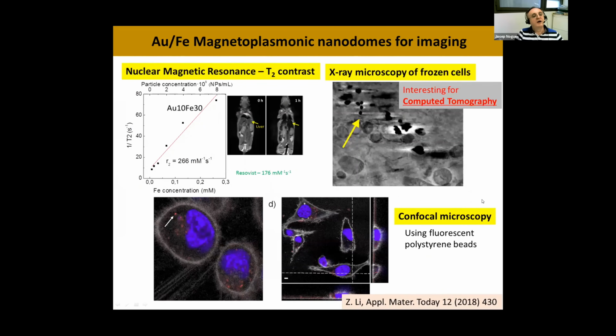Also, in terms of the imaging of these nanoparticles, first, as I said, these particles have a strong nuclear magnetic resonance. Here I put you the example of the layer with 30 nanometers of iron, which has a T2 of 266 millimolar per second. As a comparison, the commercial system based on iron oxide has 176, so we're doing much better. And here I show you an example of a real experiment.